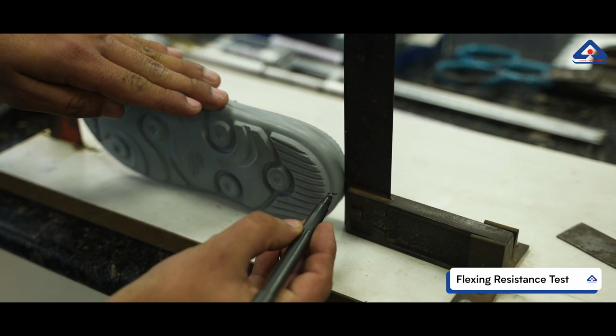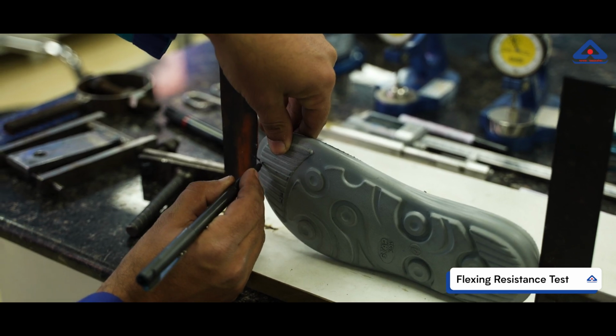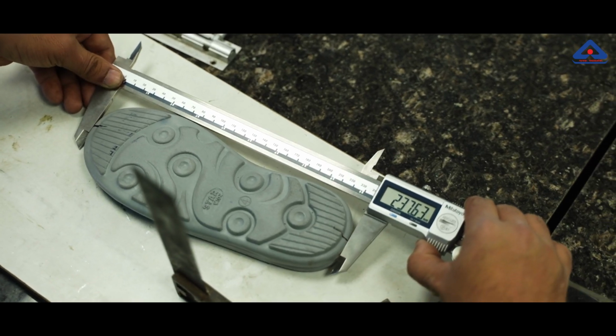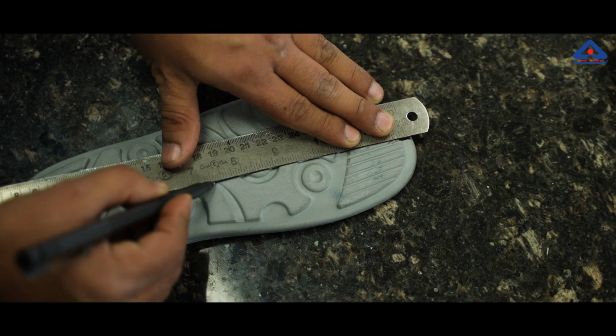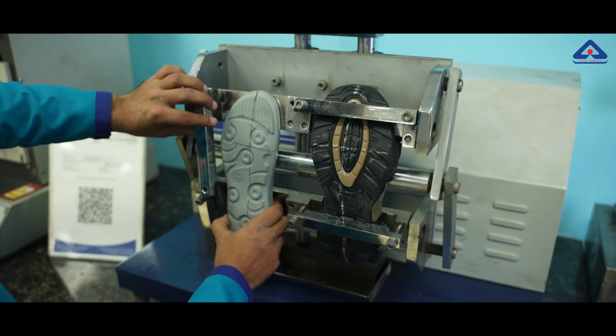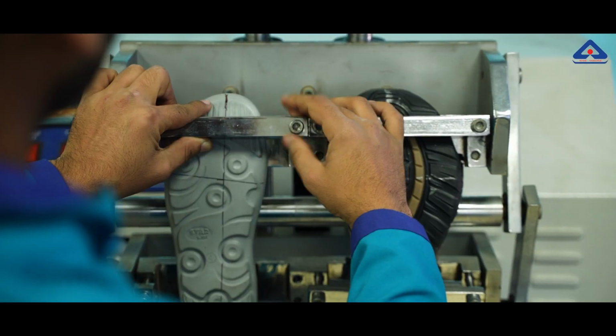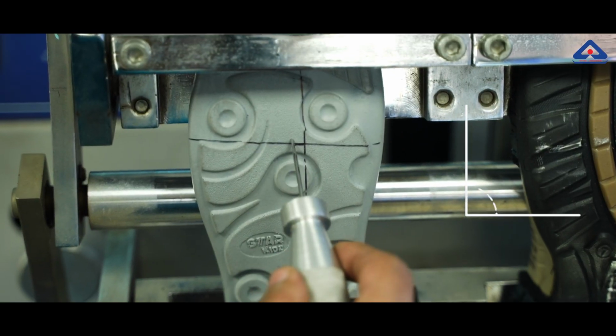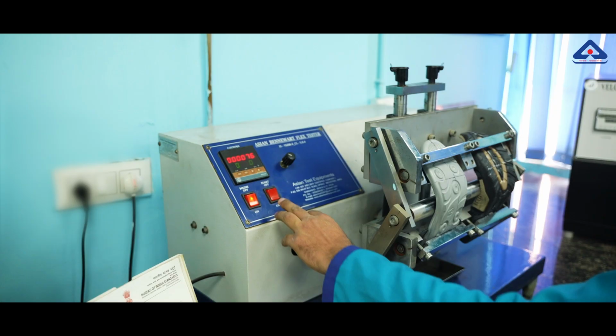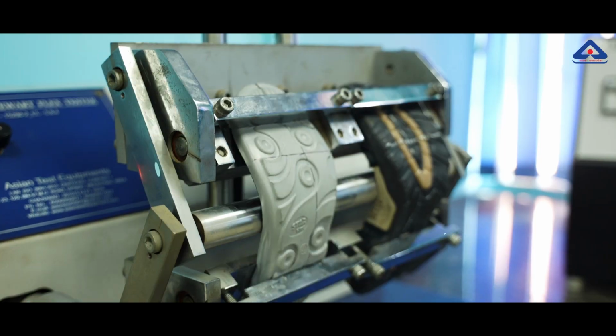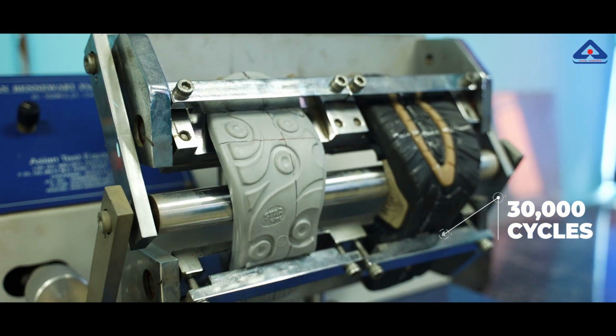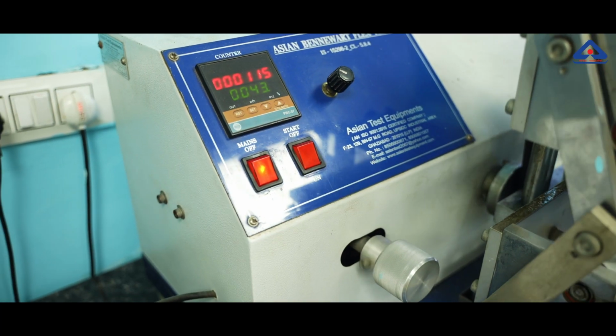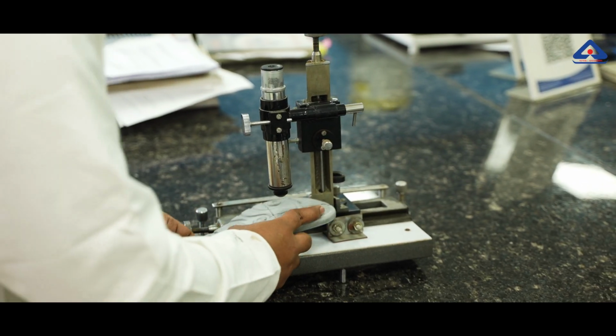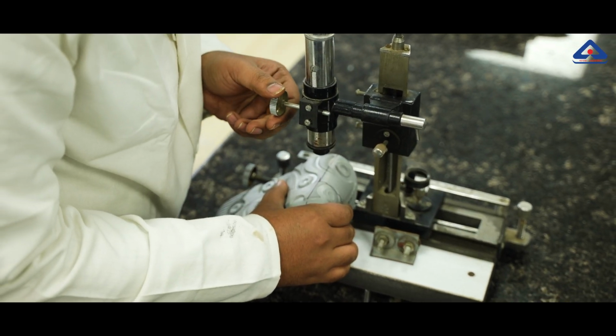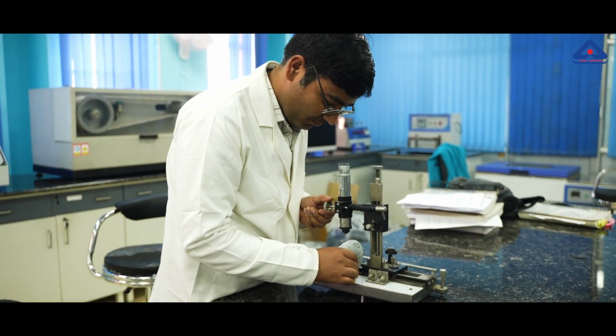In this test, the test specimen is prepared and a single incision, a cut, is made at the point. The initial length is measured with the measuring magnifier, after which the test piece is fixed in the flexing machine, where it is guided in such a way that on one side it can be bent at an angle of 90 degrees about a mandrel with a radius of 15 millimeters, over which 30,000 cycles are carried out for flex and checked for the number and dimensions of spontaneous cracks that occurred. This test simulates repeated bending, ensuring the sole can withstand long hours of wear without cracking or splitting and any deformation.